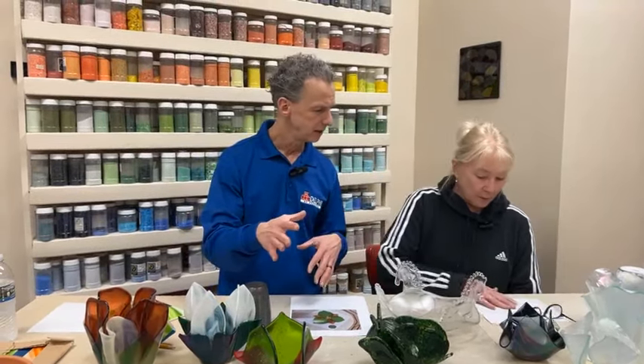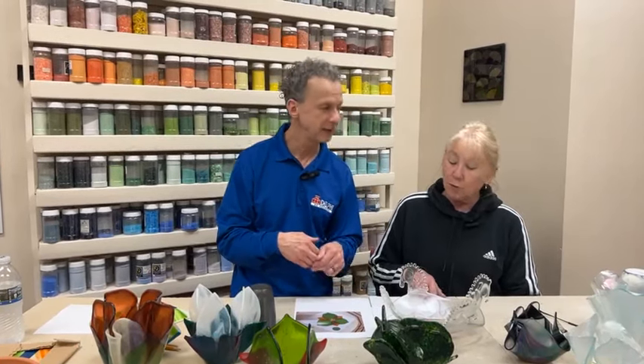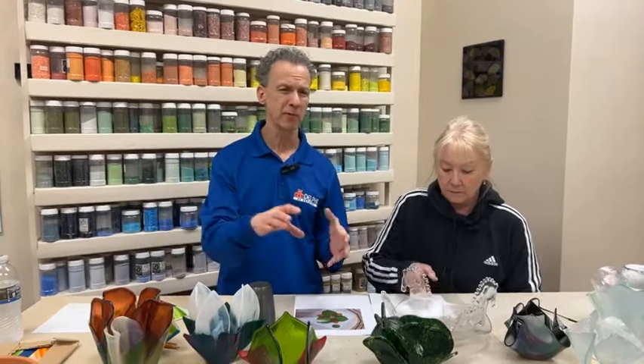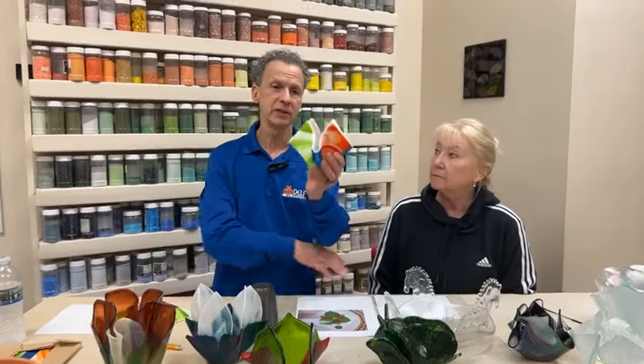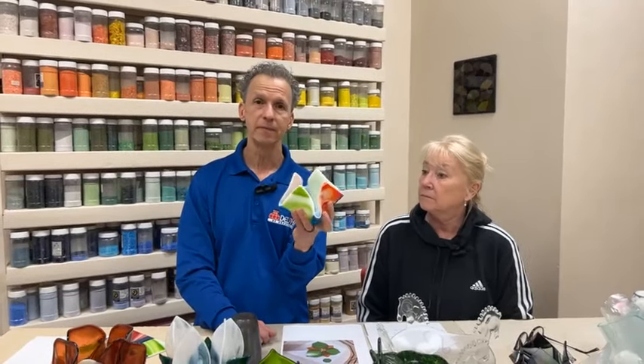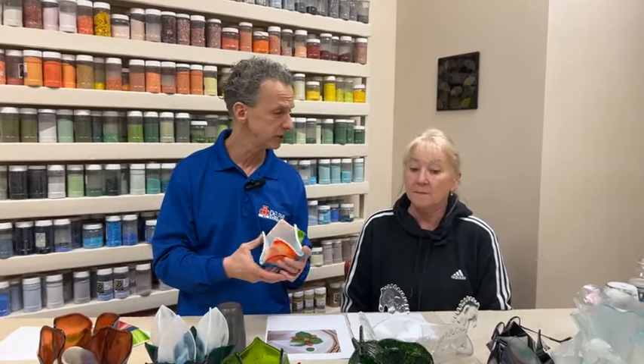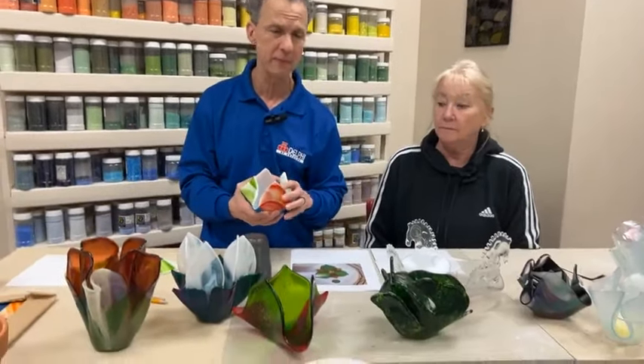We programmed to only 1200 or 1225. This is a seven inch square and I fired this piece at 1225, which gave me this look, but 1225 for these larger pieces is too hot. There's more glass, so there's more weight to them — they're affected by gravity sooner and they'll just start bending sooner. If we would have waited until 1225 on these, they would have a much different look.